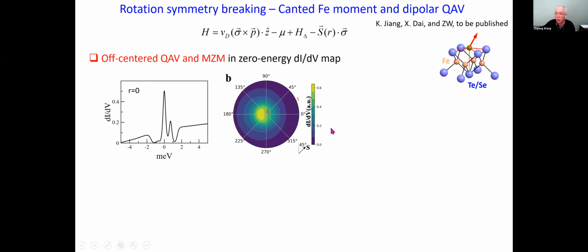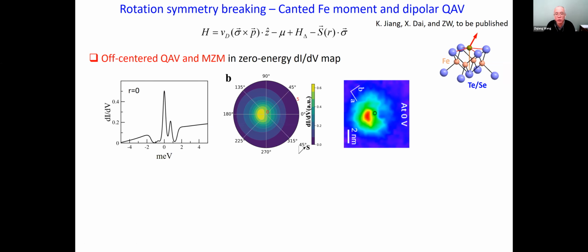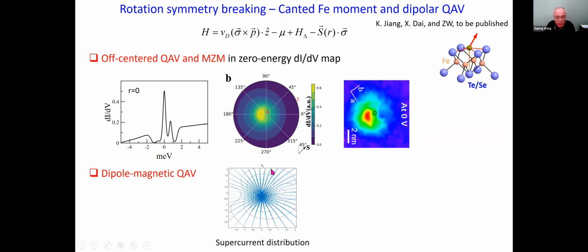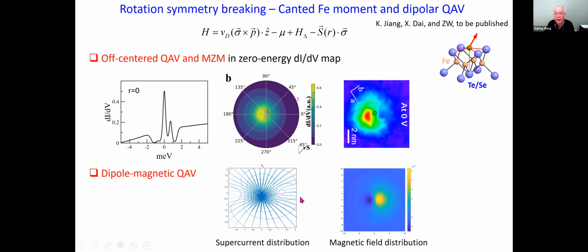Impurity center because of the breaking of the rotation symmetry. And that kind of accounts for the experimental observation. An immediate consequence of this is if you then calculate the current distribution, you find that a magnetic quantum anomalous vortex in general can have a dipole structure. In other words, if you calculate the magnetic field, on this side it is pointing, let's say, up or down, and on the other side it points in the opposite way. So the Z direction B field distribution is that of a dipole.